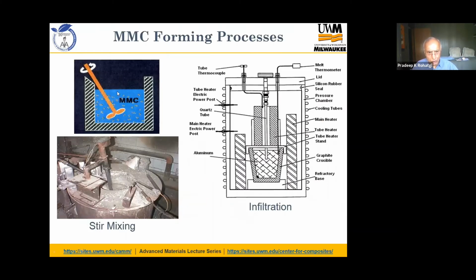And this shows a very simple schematic of how you will produce a melt of any metal, like it could be aluminum or magnesium or zinc or copper, and put a mechanical stirrer to stir it. And while you are stirring, you can add particles or fibers, micro nanoparticles, to create a suspension in liquid metal and then pour it in a mold, and it solidifies to produce a cast metal matrix composite.